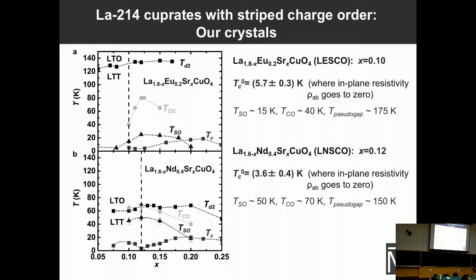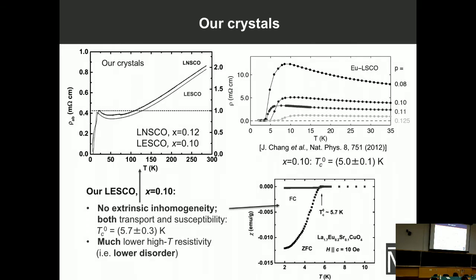I want to note that our crystals were astonishingly stable over a period of 2 to 3 years during which this study was carried out. So their properties did not change with time, which indicates that the doping was stable. It's a signature of a high quality of these crystals, and you don't always see this, unfortunately, in cuprates. Without going into too much detail, I'll also mention that we have not found any evidence of extrinsic inhomogeneities in these materials, and compared to samples of the same material, this is just an example, LESCO, ours actually have a lower disorder.